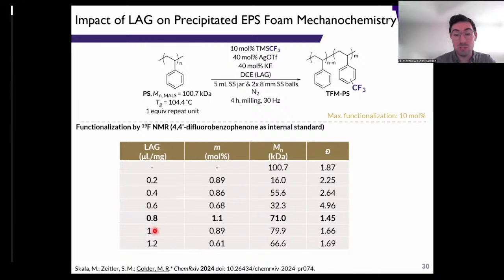We settled on a sweet spot in the middle here. Somewhere between about 0.8 and 1 seemed to be the sweet spot where we were getting about 1 mol% tagging. We still saw a little bit, about a 20 to 30% decrease in molar mass, but we thought that this would be a good place to work from.